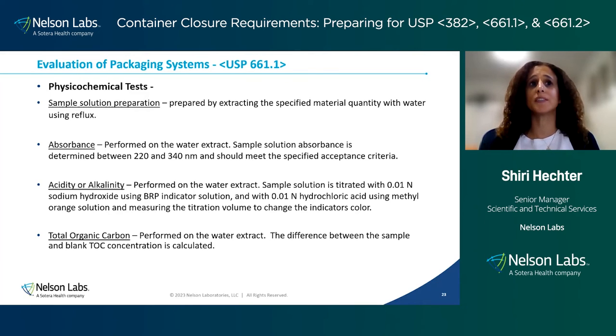The second test is acidity or alkalinity, and it's really to measure if there's any pH changes to the water extract after exposing it to reflux. And then in this case, the sample solution can be titrated with either acid or base, and the color changes with two different indicators, and the color change will be monitored, and we're measuring really the volume of titrant that we're using, either acid or base, to change the indicator color.